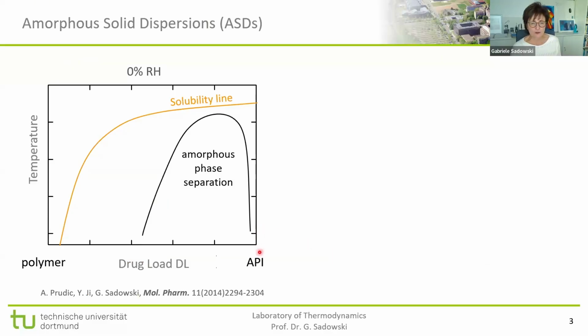So we have an easiest case, a two-component system. We have the polymer and we have the API, and we have a certain solubility of the API in a polymer. So we have the solubility line, which starts here at the melting temperature of the API, and then goes this way. So the best thing is to know this line, because everything right of the line is supersaturated. So I have on the x-axis the weight fraction of the API. This is what is usually called the drug load. Makes sense. For therapeutic effects, we need a certain drug load, so a certain amount of API in a polymer, means in a tablet. And for that, it's important to know what the solubility line is, because everything right of the solubility line means that the API will crystallize. This is what we do not want to have.